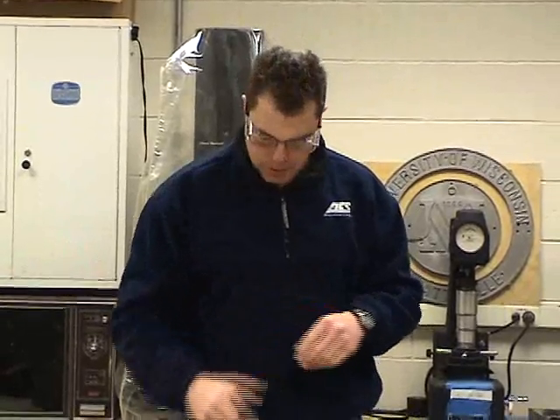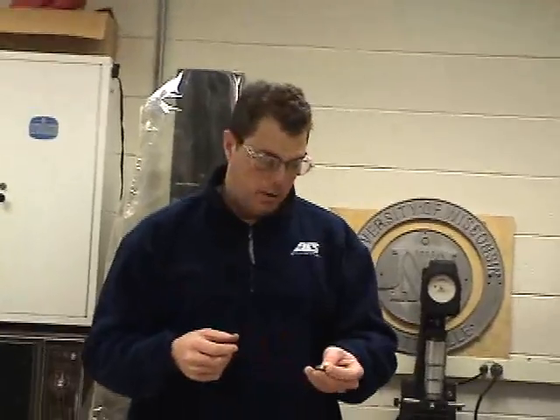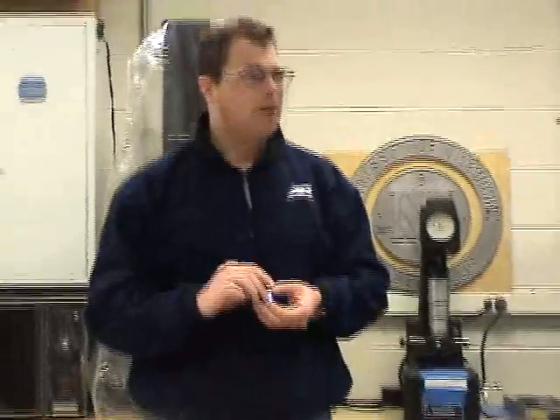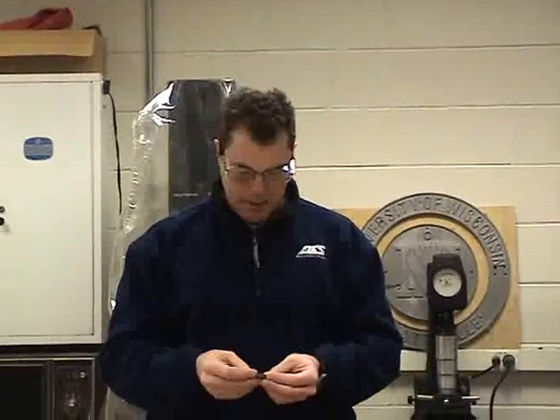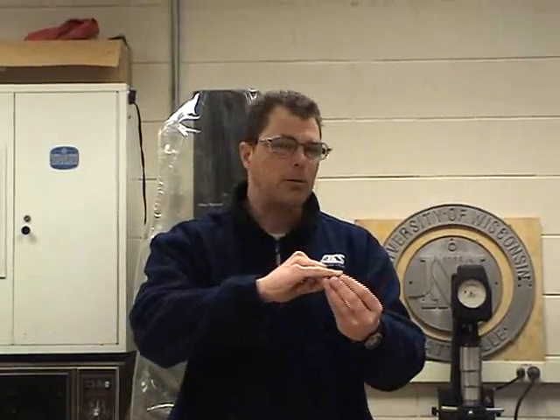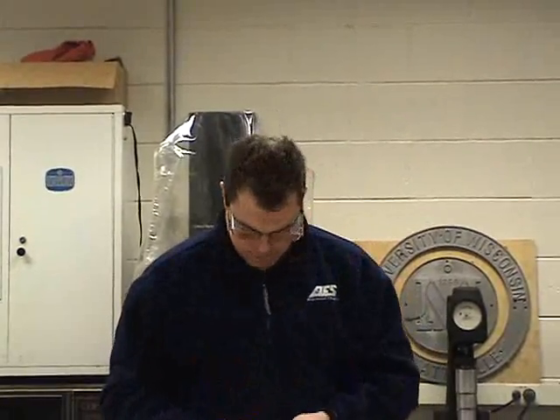The reason is because you get a lot of scale on the surface from the iron. You get a lot of iron oxide because it's cooled for such a long period of time. And if we would do that first, then you'd have to really spend a lot of time sanding it off to get down to some good steel. You lose some carbon on the surface as well when you put it in the furnace for a long period of time like that. So that's essentially the experiment.